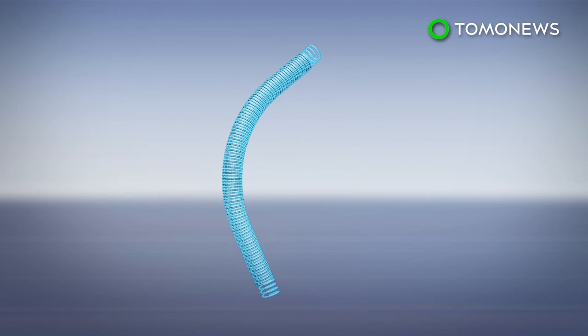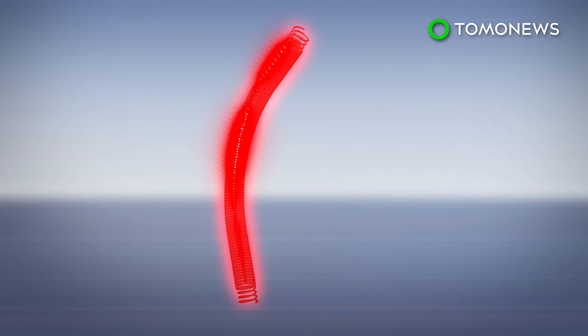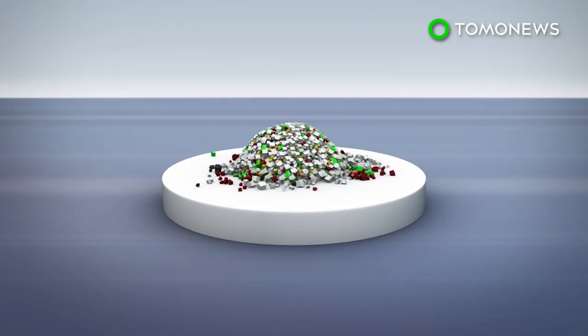The carbon nanotubes are spiral in shape and have magnetic properties. The nanotubes are coated with nitrogen and embedded with manganese in their interior. The nanotubes are then mixed with peroxy monosulfate, a compound used as an oxidizing agent to generate reactive oxygen species, or chemical reactions to break down marine microplastics.